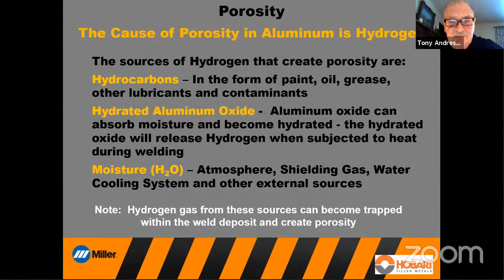And then moisture generally. Moisture can be in the atmosphere. If you're working in a humid environment and you have changes in temperature, you cross dew points and you can get condensation on your wire and your plate. You can have moisture in your shielding gas, right? You can get moisture from your cooling system if you're using water-cooled equipment and you've got any leaks, all right? And other external sources like compressed air, people blowing compressed air on the surface of the plate and it having moisture in it, and oil in it for that matter, can cause porosity.